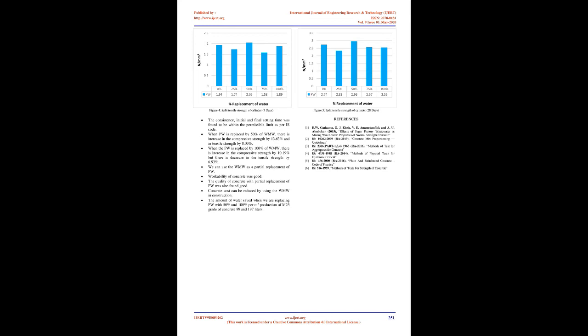From the tests performed, we can clearly say that WMW can be used in construction work, as the chemical analysis was within the permissible limit as per IS 456/2000. And it can also be used for curing purposes. The partial replacement of PW shows an increase in compressive strength as well as split tensile strength. When we replace the PW by 25%, 75%, and 100%, there is a reduction in the split tensile strength of 14.96%, 6.20% and 6.93% respectively. 100% replacement is possible as there is negligible reduction in the tensile strength of concrete. Figure 4, split tensile strength of cylinder, 7 days. The consistency, and initial and final setting time were found to be within the permissible limit as per IS code.